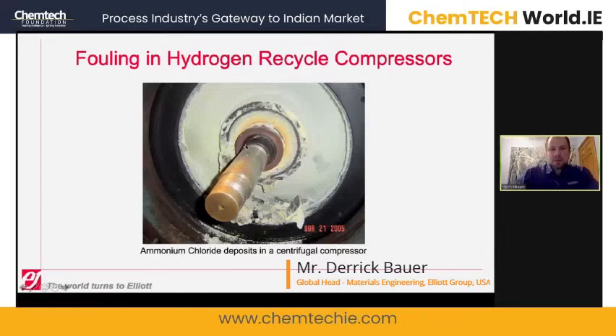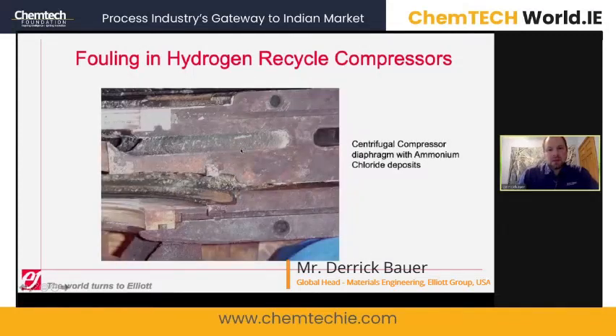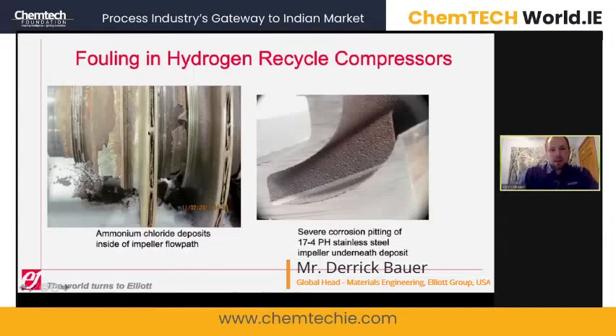It's a highly corrosive salt, basically, that deposits more prevalent on the inlet stages of a hydrogen recycle compressor. This is showing some of the buildup and the heavy fouling that occurred on the inlet end wall of a compressor. This is showing a compressor diaphragm, which is fouled with the ammonium chloride deposits. And here we see the heavy deposits on the first two impeller stages of a centrifugal compressor.